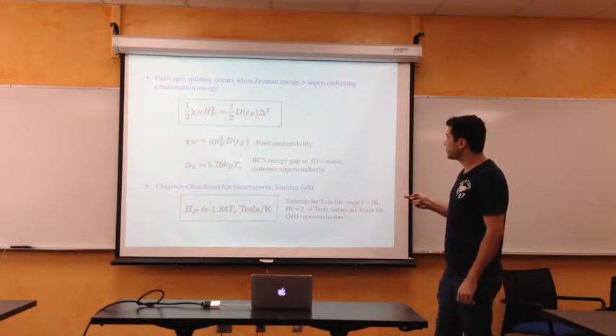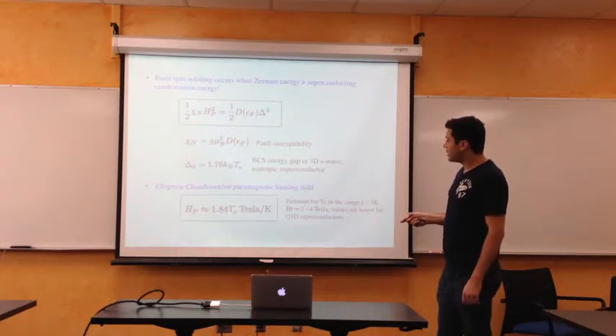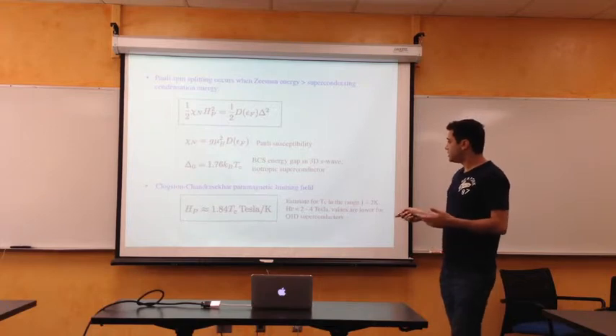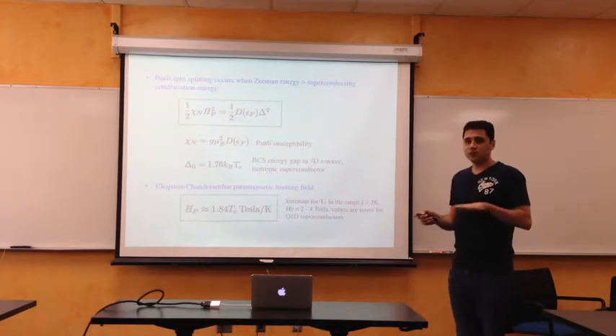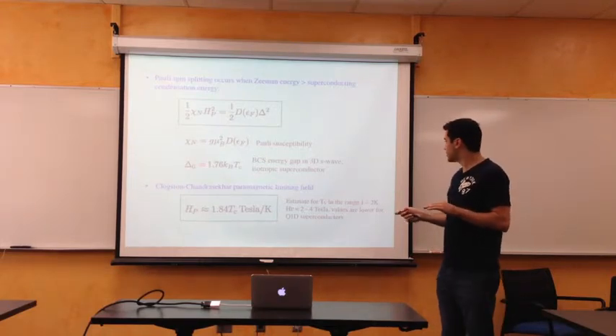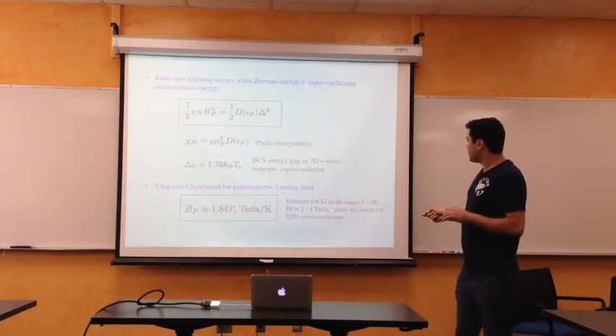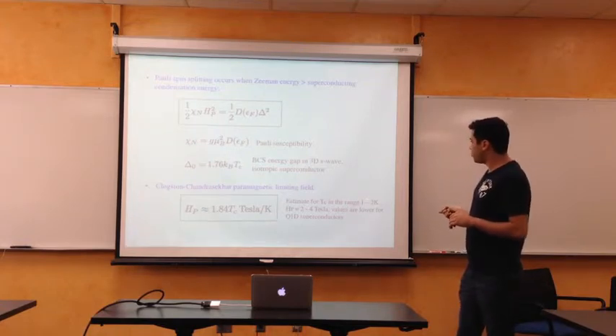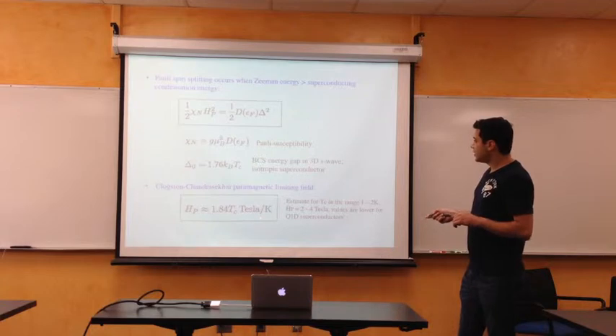So we can solve this algebraically and extract a value of about 1.84 Tc Tesla per Kelvin. What this means is that since we're dealing here with low temperature type 2 superconductors, they have a Tc of between 1 and 2 Kelvin, so you get the spin splitting field of about 2 to 4 Tesla.